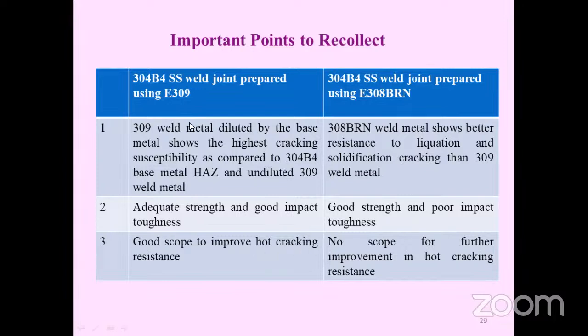And also in case of boron free electrode, we have seen that it is only because of base metal dilution that we are ending up with high cracking susceptibility, and we have a very good scope to improve the hot cracking susceptibility resistance of this material. But for the boron added material, the scope to improve is very little because the weld metal composition cannot be changed for that particular electrode.